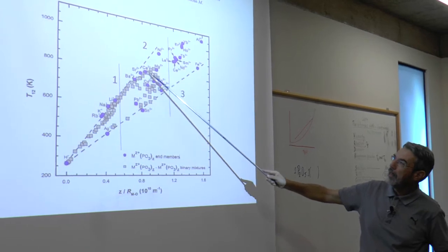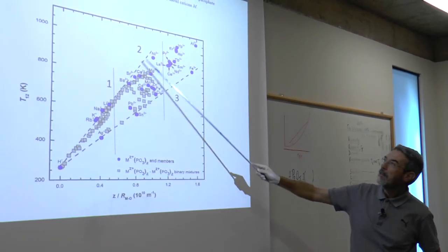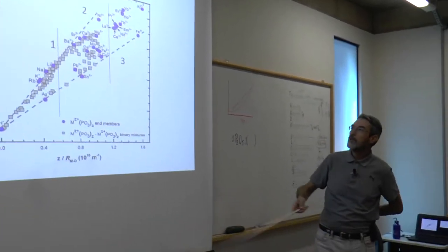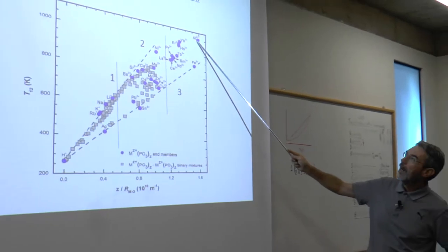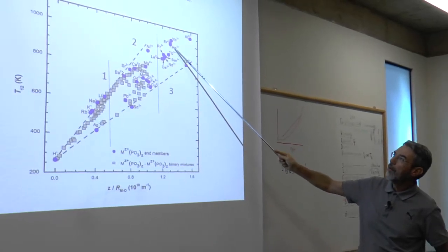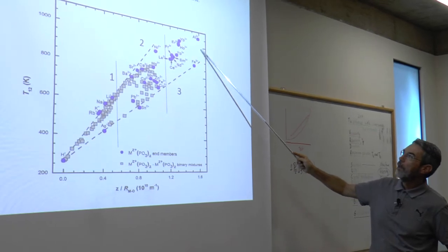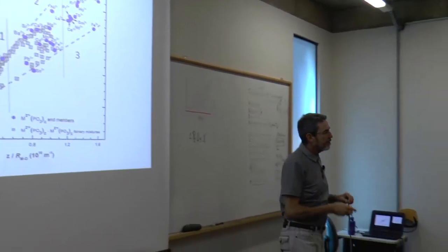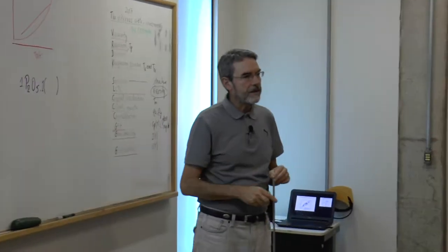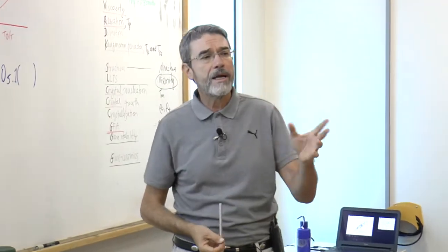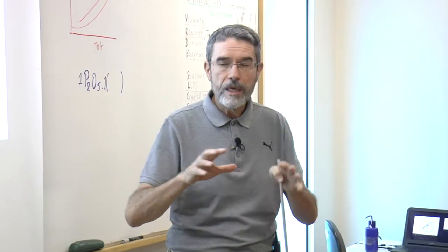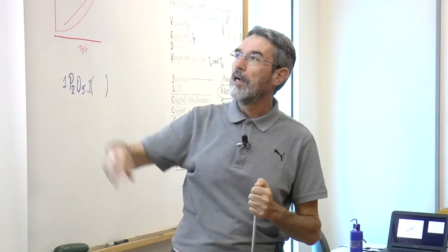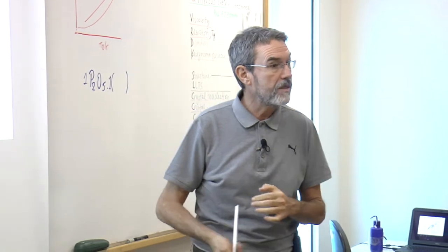Then we have magnesium, calcium, strontium, barium. The oxides with valence 2. And now with valence 3, aluminum, ytterbium, erbium, chromium, etc., praseodymium, and others. So you can control the viscosity of glasses by adding one or the other element. And this is what Graziella is trying to find out now. She's doing a thesis trying to find exactly the effect of different elements in several properties of glasses.